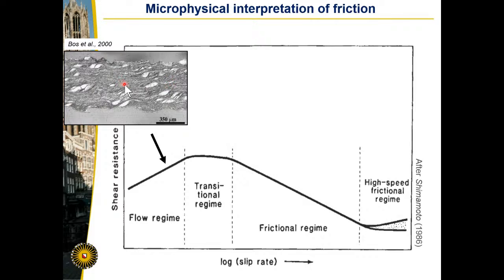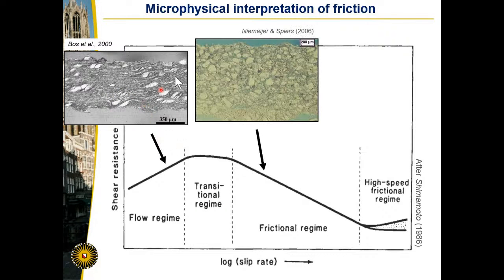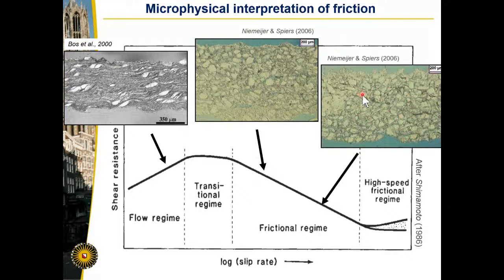And we see this in the microstructure as well. In this foliated salt clay mixture, it looks almost like a natural mylonite, so it's really flowing. But it is actually a combination of a frictional process sliding over the foliation with accommodation of the intervening clasts by dissolution, diffusion, and precipitation. If you go to the intermediate regime, we see this chaotic microstructure where we start generating porosity, and that continues until we reach some kind of critical state porosity.